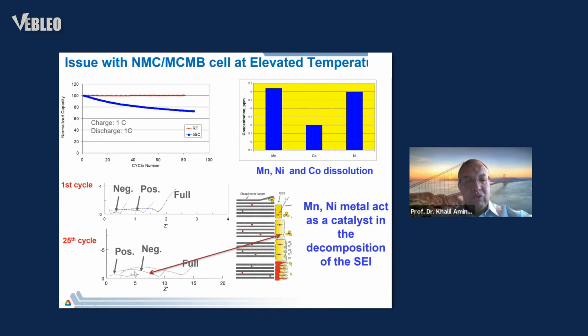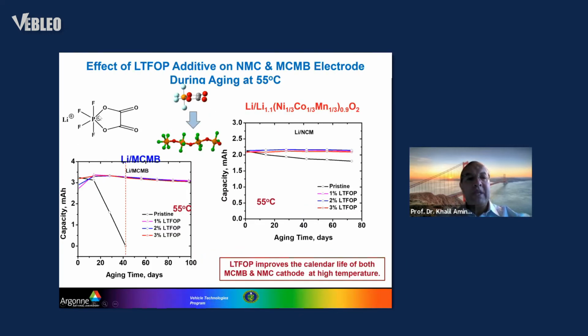So if we really want to do a validation in a real industrial cell, we have to figure out a way to put a different passivation film that is very robust to the attack by these metals. And that's exactly what we did. We developed a tetrafluoro oxalate phosphate additive, small amount, less than 1%. You put it in the electrolyte, it polymerizes and forms a very stable, uniform film at the surface of the anode. This is a DFT calculation that gives us how the polymer is formed.